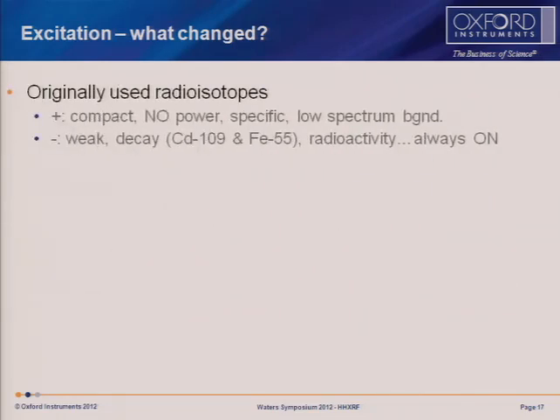In excitation, originally isotopes were used. Well, why? Well, actually, they're tremendously compact, really small, the size of a thimble, the end of your finger. Yes, they need some shielding, but that doesn't make them much bigger. They require no power. And for a system that's going to go out and work on a battery for the whole day, that's a big benefit. And they actually have real advantages in some applications where those specific lines, let's say from an Fe-55 source at 5.9 keV, can be particularly effective.